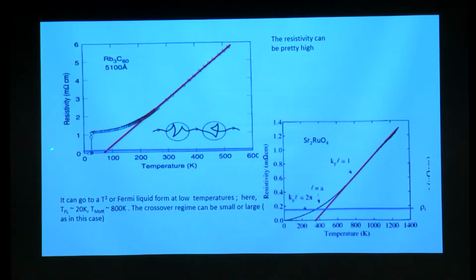There is a class of systems in which the resistivity increases linearly with temperature, but if you go to very low temperatures, you find that yes, it goes quadratically with temperature. And that makes many people very happy, because quadratic temperature dependence is what you expect in a dirty Fermi liquid. So it's Fermi liquid, good. But then it shows linearity of resistivity at high temperatures. This regime can be small or large.